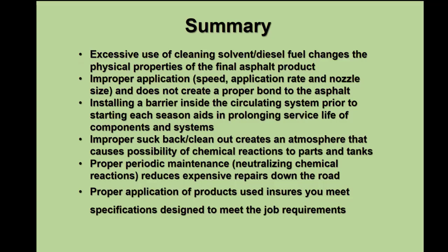Cationic emulsions are blended with hydrochloric acid. Hydrochloric acid left in a tank will actually eat away at the metal. It eats away at the metal in the bar, the joints, and the tank itself. I've poked holes in the back heads of trucks that have had material left in them for a long period of time, like over winter, and the fumes from the cationic emulsion, the hydrochloric acid, actually will etch away at the tank and eventually eat holes in it, or the bar system or anything else. So if you circulate a barrier of hot oil or something inside a tank prior to using it, let it set and cool down, you can use that tank all summer long.